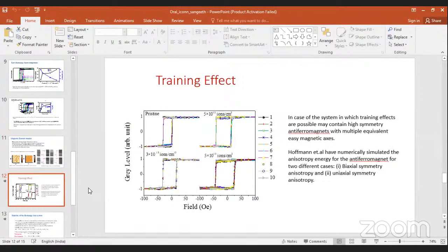Moreover, the training effect, that is repeated cycling of the hysteresis loop, will reduce the coercivity and exchange bias. But here the training effect is absent. This relates to a simulation called Hoffmann's model. From it he explained that the uniaxial anisotropy present in the antiferromagnet contributes to the absence of the training effect.